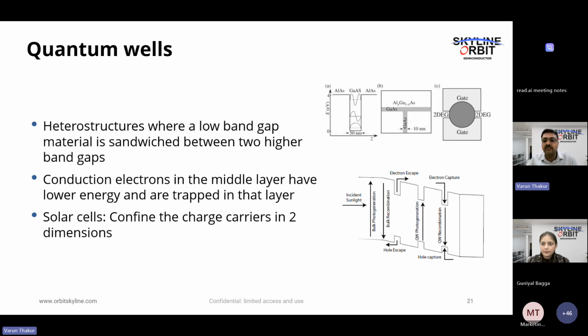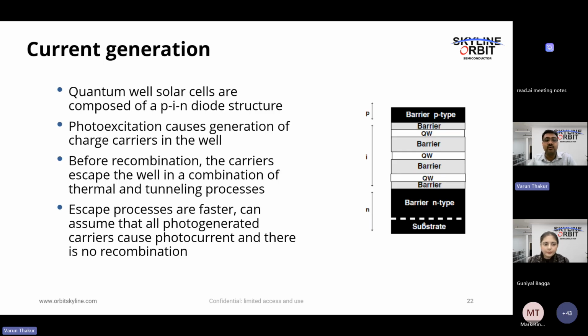So let's look at one element which is called a quantum well. Because we are growing films which are nanometers thick, quantum mechanics takes over at those levels. A quantum well is basically a region of the solar cell where one lower bandgap material is sandwiched between two higher bandgap materials. The idea is that we want to trap the charge carriers in this low bandgap region so that we can maximize the current, basically increase the photocurrent, right? When light shines on the solar cell, if you have quantum wells in the active region of your structure, the photogenerated carriers will be trapped in this layer, and the extra time that you get will increase your efficiency proportionately, right? So this is the advantage of quantum wells. And I've just given the mechanism through which the current is generated.